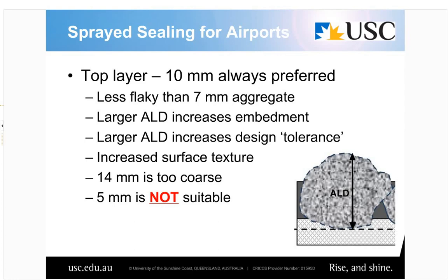And the 5mm seal, that's really leaving you zero tolerance. I've seen multiple airports with 5mm seals over either 10s or 7s underneath, and almost invariably there are bits of those runways where there's way too much bitumen for the stone, and other bits where there's nowhere near enough. As a result, there'd be flushed bits of seal almost immediately adjacent to bits of seal where the stones have all been whipped off because they weren't ever stuck properly.